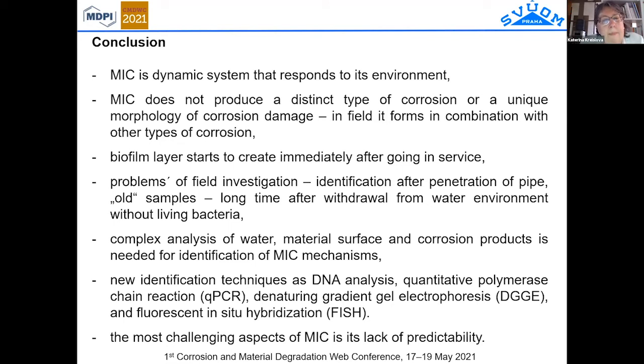When we try to identify if the corrosion was accelerated by this type of corrosion, we need a complex analysis of water, material, surface, corrosion products, and all the techniques which are available to identify and put together this mosaic, to be sure if this corrosion was caused by the combination of environment and microbiological activity of the water. So what was necessary, and it was mentioned in some previous presentation, is that we need to apply the new identification techniques, but in a more simplified way, to be applied not only in the high equipment laboratory, but in the field for easy identification, and especially for the